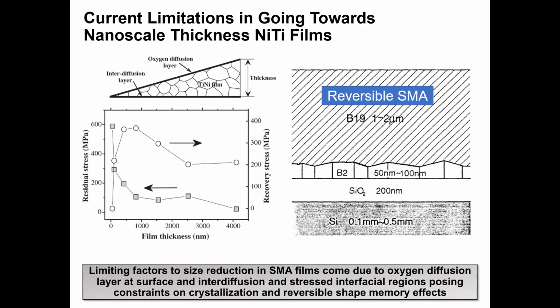So therefore, as shown in this figure on the right-hand side, typical best practices thus far has been to use sufficiently thick films of 1 or 2 microns or even thicker to increase the volume of material available and capable of undergoing a phase transformation. So in order for nanoscale SMA actuator volumes to exhibit shape memory effects, care must be taken to limit these constraints. So for example, lowering the deposition temperature could be expected to help alleviate some of the interfacial diffusion regions at this film substrate interface, and also reduce some of the interfacial strains due to CTE mismatch.